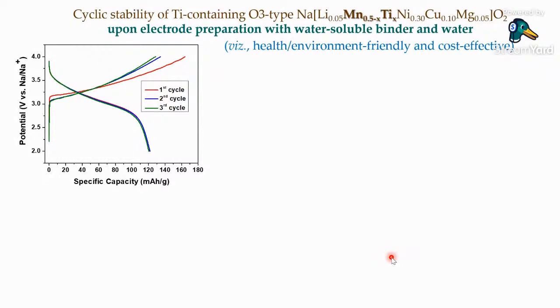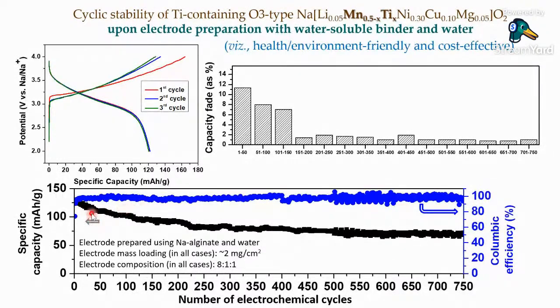Now comes the most important part. Okay, fine, we established that this cathode material is water stable, but can we prepare an electrode using water based slurry and not use NMP? Now we did that. So this is the cyclic stability exhibited by the cathode prepared using water based slurry, and one can again see that it is fairly stable, even though the electrode was prepared using water and there was no NMP used in the electrode preparation.